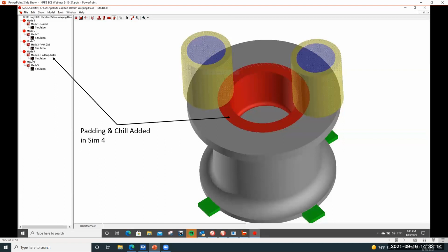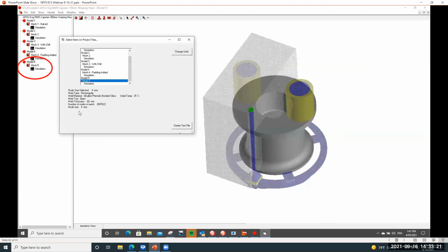casting. And then finally, our final simulation, or simulation number 5, that was done with the entire gating system and also done using what's known as a plane of symmetry. You can see here that the casting itself is radially symmetric, but when we add risering and gating, we have a plane of symmetry or a mirror image right down the middle.